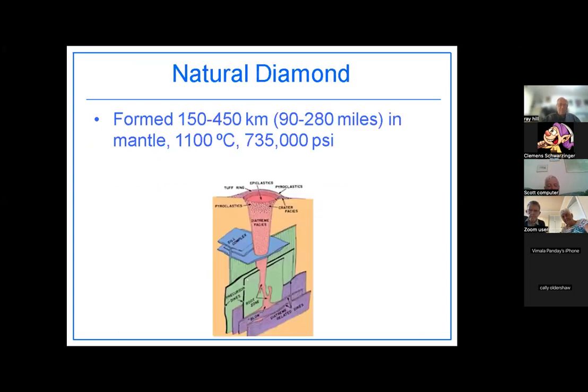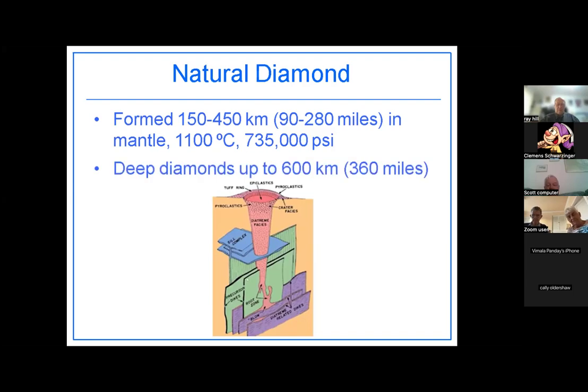So your natural diamonds are formed anywhere from 150 to 450 kilometers deep. By the way, there are deep mantle diamonds now that apparently go much deeper, and those are your pinks and reds. But down at those depths, you have a temperature of about 1100 centigrade and about 735,000 psi. So diamond is kind of an interesting thing in its formation in the natural world.